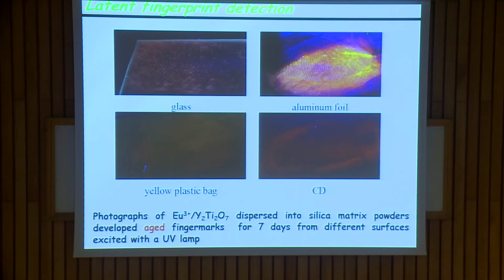We applied our material for detection of latent fingerprints from non-porous surfaces such as glass, transparent plastic bags with different colors, blue and yellow, also aluminum foil and a scratched CD, and also to porous material such as green leaf paper, and we successfully identified the details of the latent fingerprint. Also, we applied our material to aged fingerprints of 7 days, exposed to the air and moisture, and as we can see, the fingerprint is very clear.